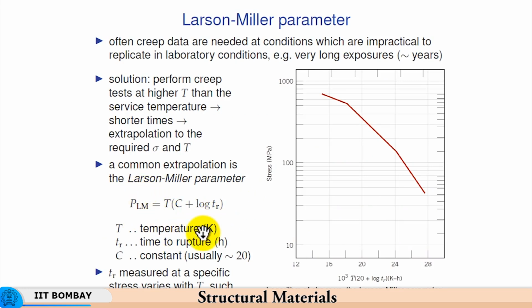which is given here. And then you plot this parameter in terms of C plus log of time to rupture, where the time to rupture is in hours, and C is a constant at 20. One plots this in terms of 1000. So, this is 12,000, 16,000, 20,000, 28,000 and so on. The Larson-Miller parameter is plotted in terms of thousands.